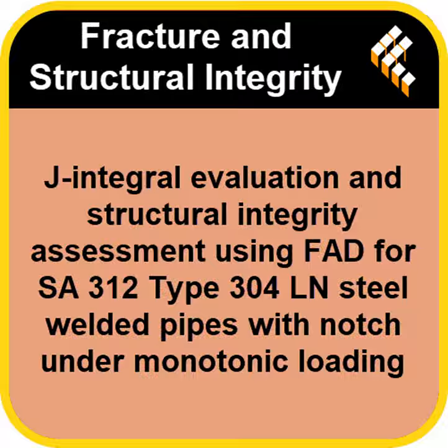When they used that formula, 2 of the 3 specimens ended up skirting the very edge of that stable region on the FAD plot. So they weren't technically unstable, but they had effectively zero margin left. They were right on the line, or just barely inside it. Correct. They were specifically described in the analysis as being marginally below the failure assessment line.